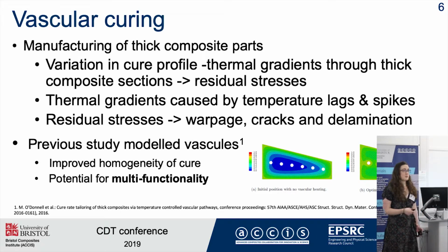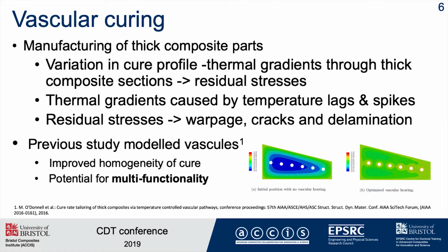Previous work here at the University of Bristol looked to model using vascular curing as a potential way to increase homogeneity of cure and the potential for multifunctionality post-cure. So, as part of the PhD, I've then looked at the experimental setup, so how we implement vascular curing experimentally within thick composites, and we've had some really promising results so far. I've been able to show that we can reduce the exotherm of cure and put the heat into the cure quicker. So hopefully we can look to optimise cure cycles